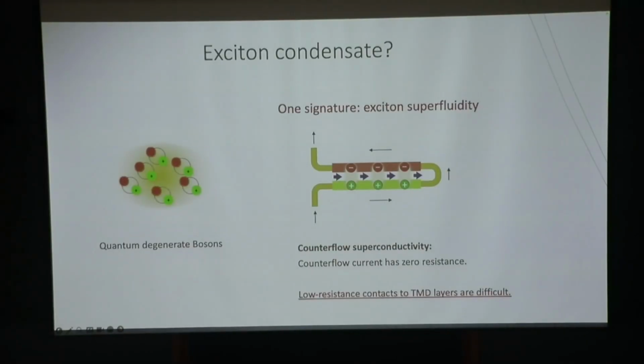So one proposal by theory is measuring the so-called exciton superfluidity. The idea is, if the exciton is a global condensate, then the exciton can transport with no dissipation. If you convert it into electron-hole movement, imagine the exciton is moving along one direction: the positive charge moves in that direction and the negative charge moves in the opposite direction, which means the electrical current moves in the same direction. So if you can do a counterflow measurement, where current flows this way and that way, and then measure the resistance of this counterflow, you should see zero counterflow resistance.